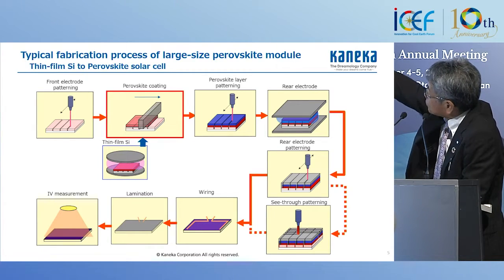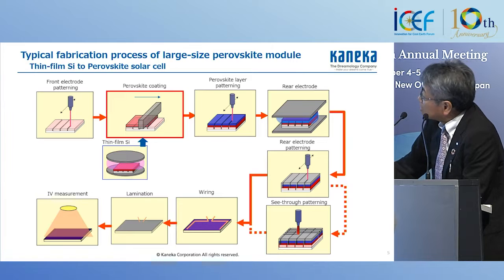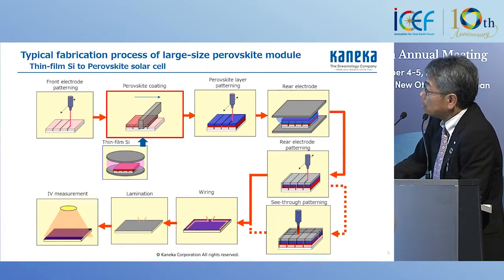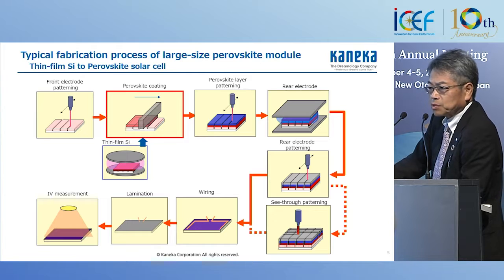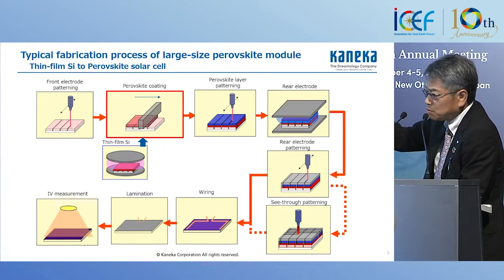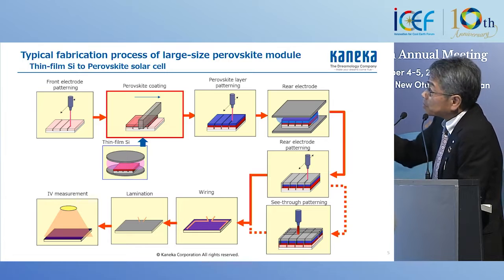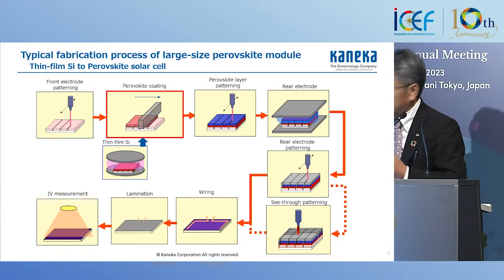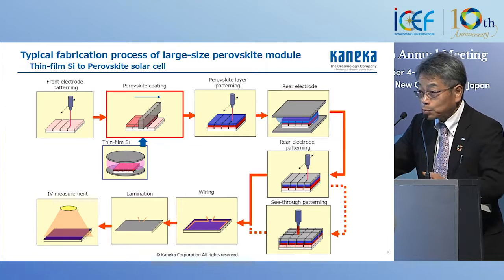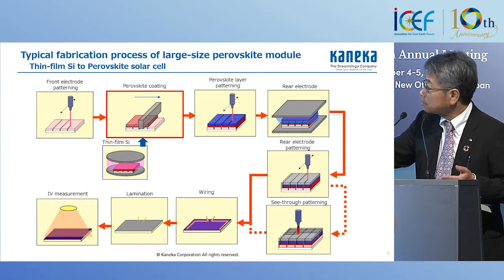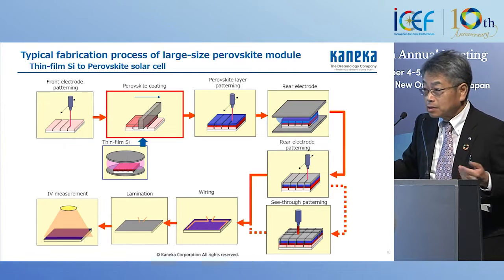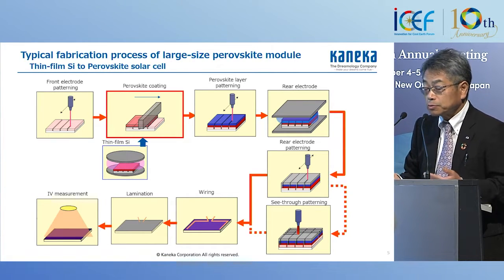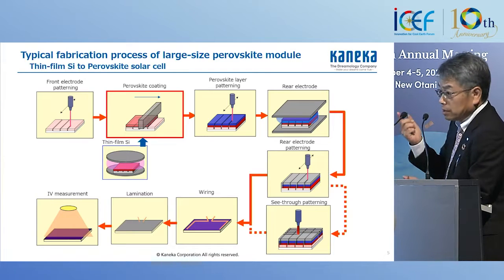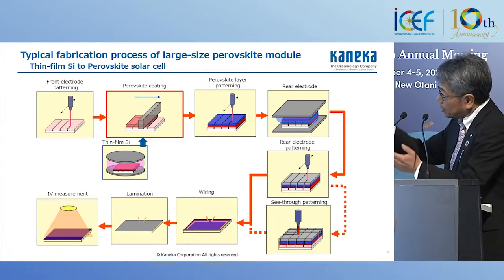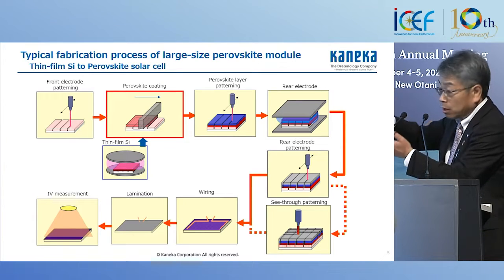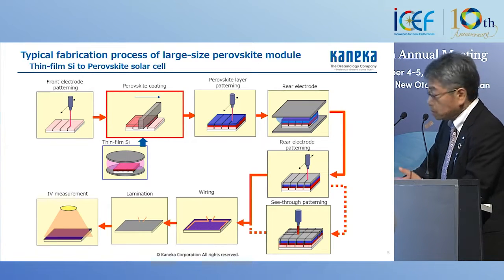And in the see-through case, we sometimes remove the active layer by see-through laser patterning. This is a very robust process, and moreover, a fully integrated process. Namely, once we input the glass, we get the module product, which has already been measured, laminated, and wired. A fully integrated process. This is very important. And usually for one factory, only 2 to 3 hours, we accomplish everything, completely different from silicon.